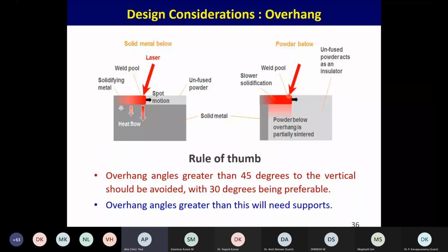Another aspect is the overhang structures. When you make a track on a solid block, you have a very good heat flow. When you have overhang structures, either you will not have material, as in case of DED, or you have powder material sitting there, as in powder bed fusion. In both cases, the heat flow will be much lower than what we have here. So the thumb rule is you should try to avoid any angle more than 45 degrees, and 30 degrees is very good. That is the sort of thing people think about.